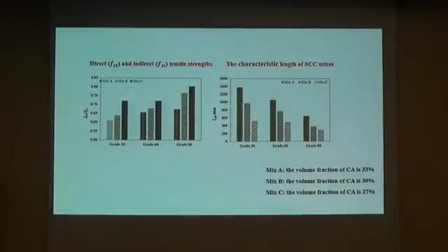As for the direct tensile strength of concrete, it is known that direct tensile strength is 2/3 of indirect tensile strength. Direct tensile strength here can be found by using an inverse procedure, and indirect tensile strength can be found by testing the splitting tensile strength of concrete. From these figures, the ratio of direct to indirect strength is dominated by the coarse aggregate volume fraction. The final parameter is the characteristic length, which gives an indication of the ductility of the self-compacting concrete mix, also dominated by the volume fraction of coarse aggregate.